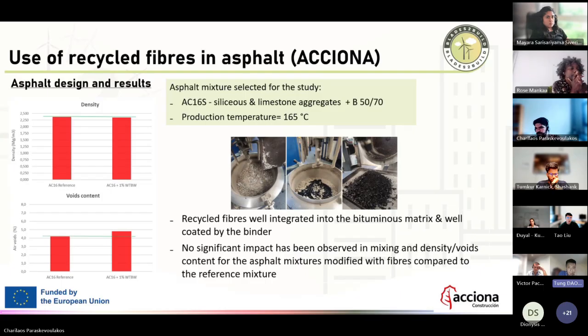So the recipe that they selected for the study is the AC16S. AC is asphalt concrete. 16 is the Dmax, the maximum dimension of the aggregate, so 16 millimeters. S, I think, refers to semi-dense, a type of asphalt with siliceous and limestone aggregate. They use the bitumen 50/70, which is the hardest bitumen grade, usually used for hot weather materials.